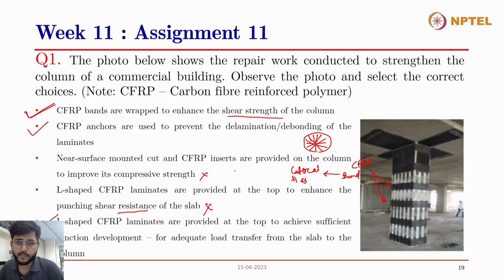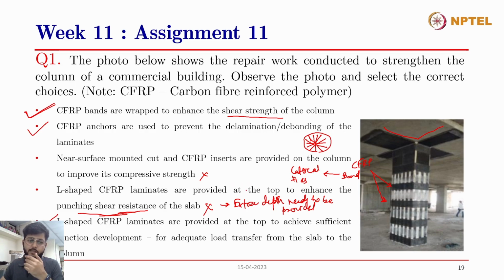Near surface mounted cut CFRP inserts are provided on the column to improve its compressive strength. No, this is not the case in the given picture. And L-shaped CFRP laminates are provided at the top to enhance the punching shear resistance. Punching, as Dr. Satish also mentioned, for punching shear resistance to be increased, extra depth needs to be provided. And as we can see in this flat slab system, there is no extra depth provided over here. We have only provided these L-shaped CFRP laminates, and they do not enhance the depth or the effective shear cross-sectional area for the punching shear resistance to be increased, and therefore this is not the correct answer.